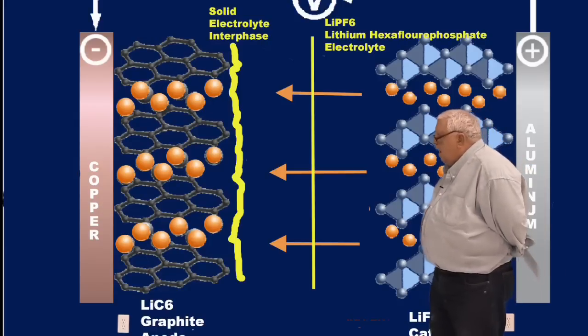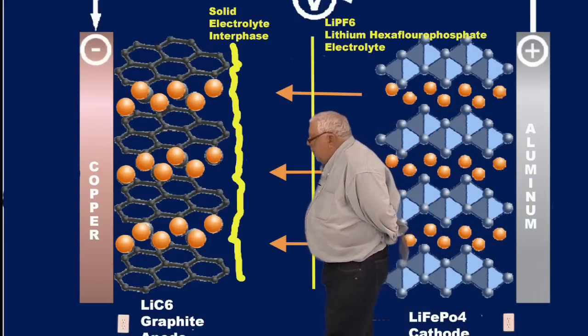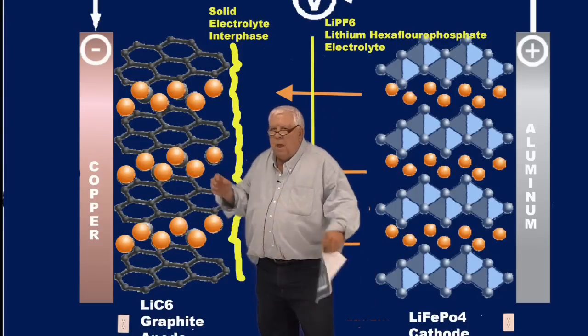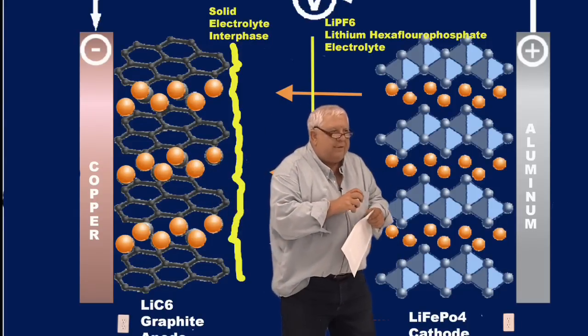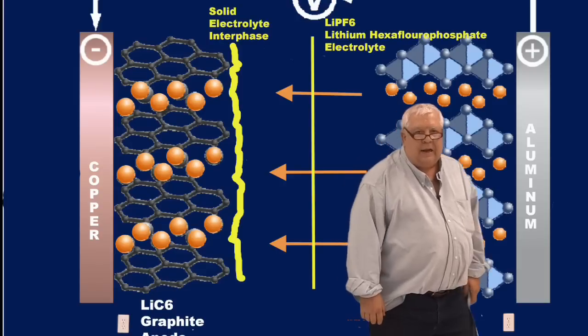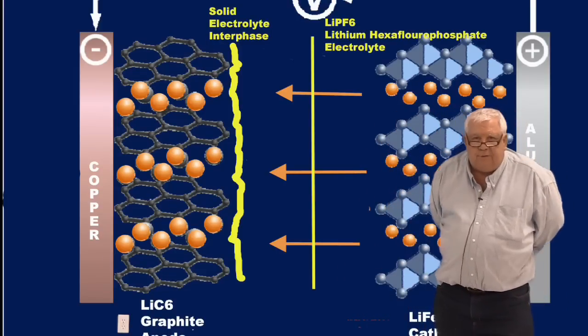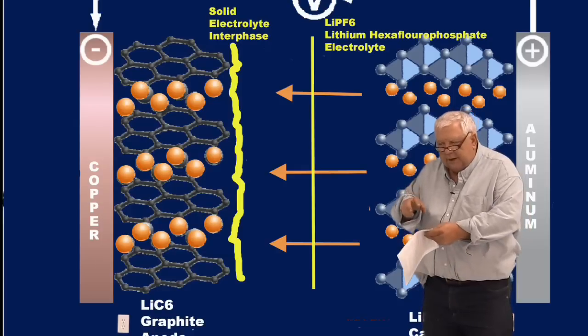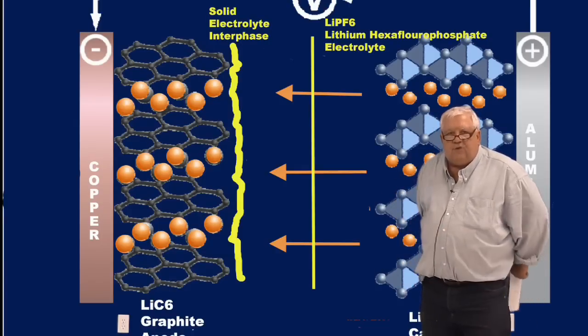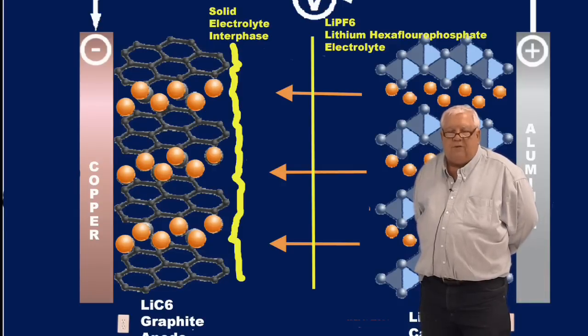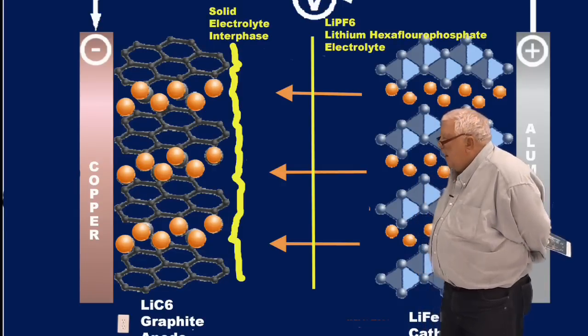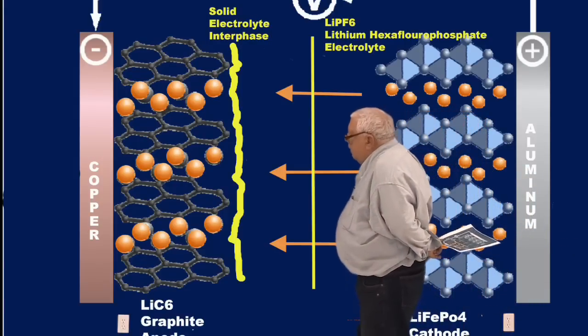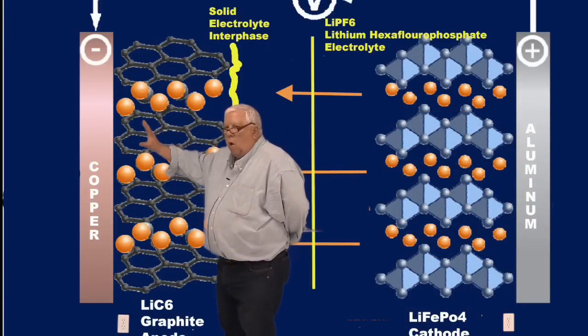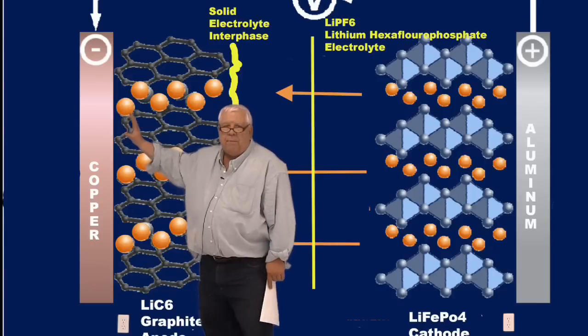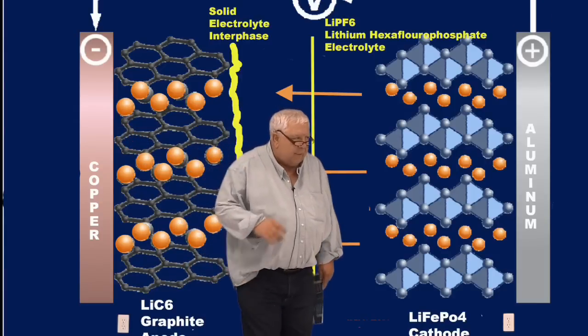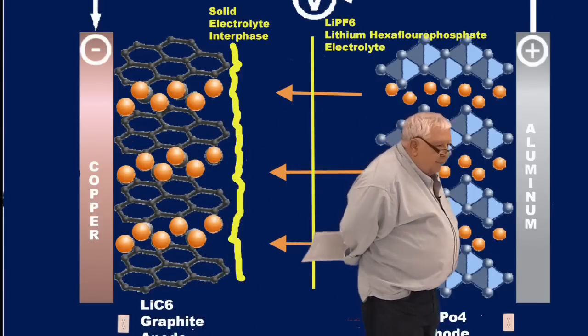The process of intercalation of lithium ions into the carbon causes the lattice to expand mechanically, and it fractures in some cases. Intercalation, it expands; deintercalation, it shrinks back, and this wears out our carbon, and it breaks into pieces. The SEI layer kind of functions to hold that wall of crumbling bricks together in place and extends the life of the battery. However, there is a diffusion delay